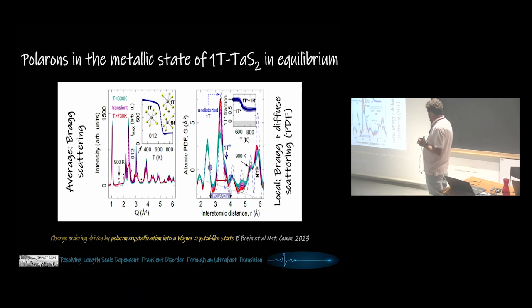will convert the system from 1T type environment, which is octahedral coordination of tantalum, to a 1T plus 1H mixture, 1H being trigonal prismatic. And as it turns out, in all the polymorphs that could appear, you will have a 50-50 mixture. So it's either 4Hb or it's 6R. And so interestingly enough, if you follow the PDF signal across this heating, you do see that the polaronic signal drops by 50%. So this suggests that the precursor polaronic state is associated with 1T type layers.